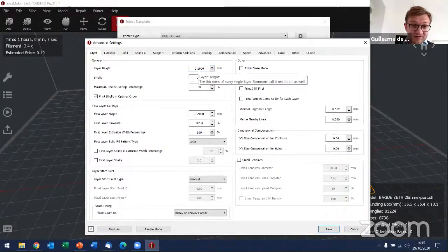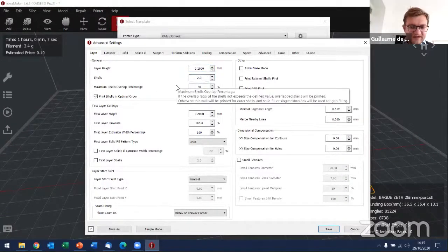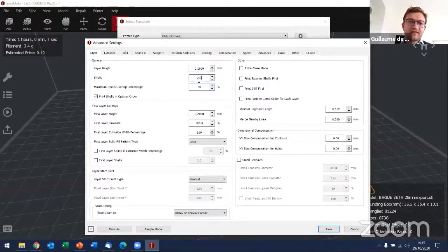Second really, really important parameter is the shell. You may not have seen, and I'll show you again later on, but the part is divided in a slicer between the outside region of the part, which is called the shell, and the inside, which is going to be called the infill. Here we are going to define the thickness of the shell, and we define it in numbers of nozzle size, basically. So the nozzle is 0.4. So if we put 2 shells, the total shell is going to be 0.8 millimeter. This seems like a reasonable figure. We can leave it here. We could want to do it a bit thicker and maybe put 3 shells. Why not?